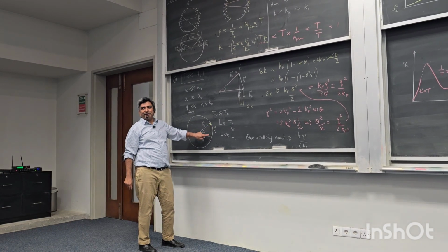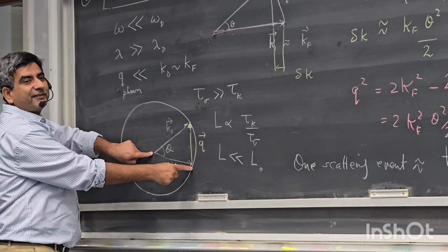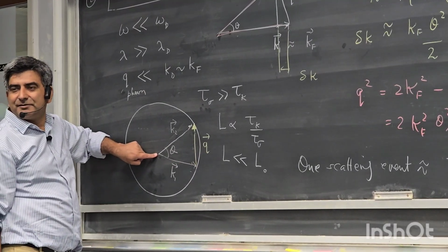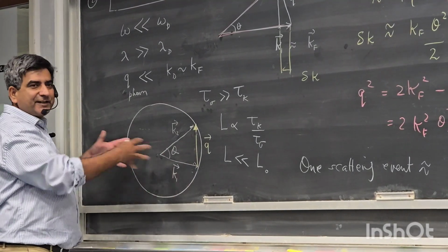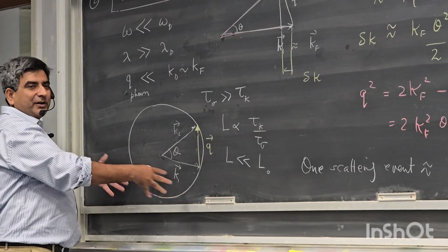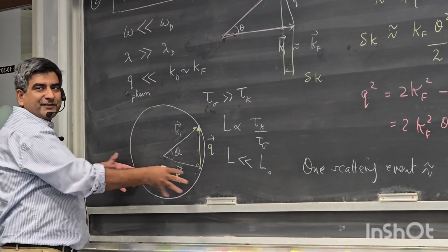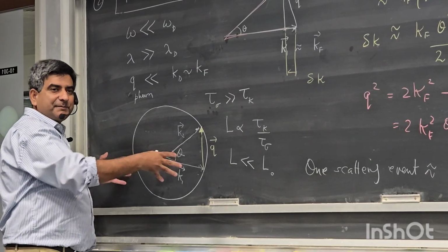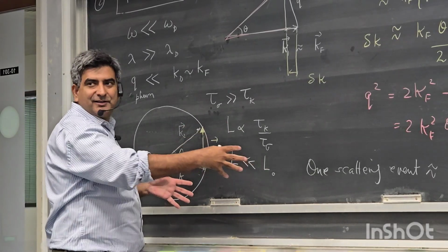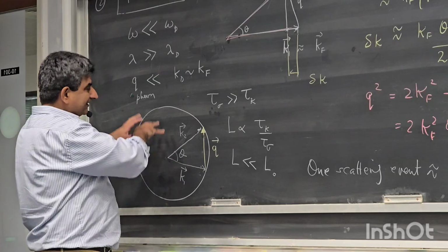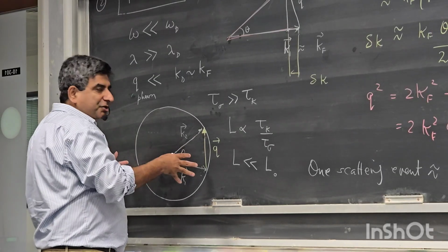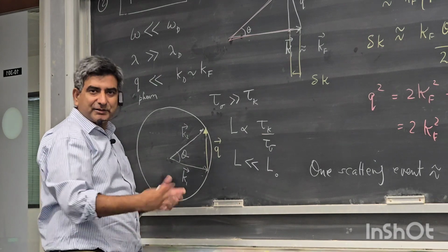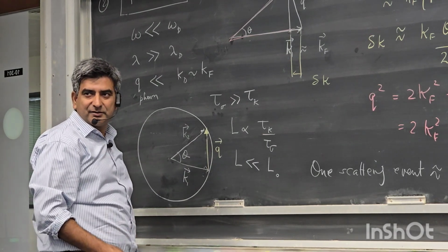It does not have a long enough wave vector to cause this electron wave vector to flip from one side to the other. But this entire picture is drawn inside one Brillouin zone. This Fermi sphere is in one Brillouin zone. But the reciprocal space picture is periodic. So you have the first Brillouin zone, this K sphere is then replicated, it's periodic. We know that the reciprocal space is periodic.